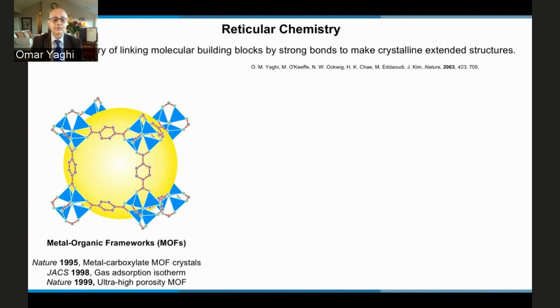And in 1998, this strong bonding and the ability to assemble multiple metal ions and use them as corners or as intersections in a network showed that this arrangement could produce architecturally robust structures, as evidenced by the very first gas adsorption isotherm made on a metal organic material. And this gave us the porosity parameters that allowed us in those days to compare our materials with well-established materials such as porous carbon, metal oxides and zeolites. As I will show later, in 1999, we showed how this strategy, using MOF-5 shown here, can produce ultra-high porosity.